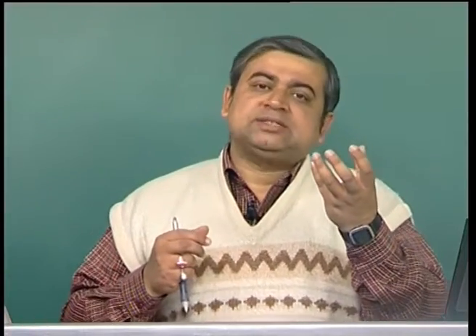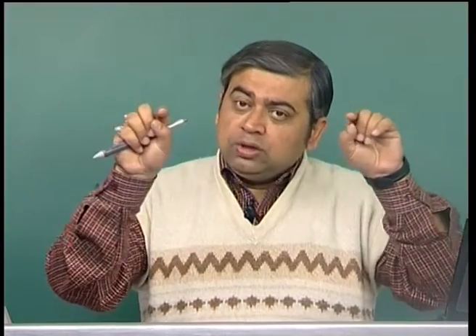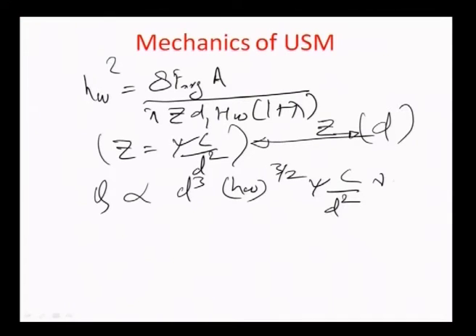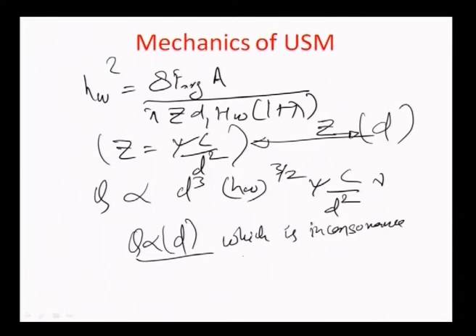So that is why the z value does not alter; the z value is still inversely proportional to the square of the diameter, because that is ultimately the determinant of the grain to grain spacing. The average diameter of the grain is the determinant of the grain to grain spacing between the tool surface and the workpiece surface, assuming a fixed tool area. So therefore, this expression becomes conveniently changed, and Q becomes proportional to the average grain diameter d, which is in consonance with, of course, the experimental observation. And therefore, this gives you the total prediction of Shaw theory towards the different parameters involved in the material removal rate of a USM process.